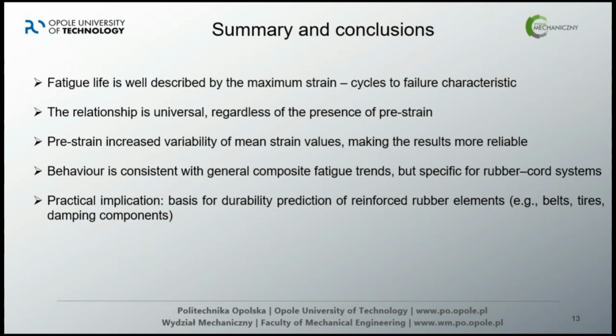Yeah, it fails about the actuator in the middle. That's one thing, and it usually cracks either in the rubber, but usually at the interface between the rubber and the reinforcement. So it's more the interface than the actual fibers. Okay. We will analyze it later with the microscope and also the X-ray, so we'll have the exact results. But my analysis tells me that it's on the interface.